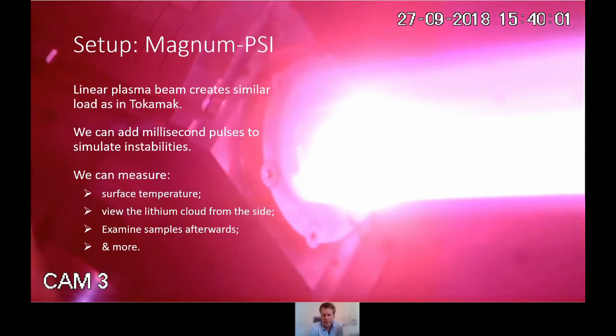We can add millisecond pulses on top of a steady state load. So you can have a steady state, you can turn the plasma beam on for hours, but you can add millisecond pulses to mimic plasma instabilities on top of this. For those in the fusion field, of course, I refer to the ELMs. And then we can measure a lot of things, but today I'm going to take a look at surface temperature, and a view of the lithium cloud that we can see from the side with a high-speed camera. And of course, we can examine the samples afterwards.